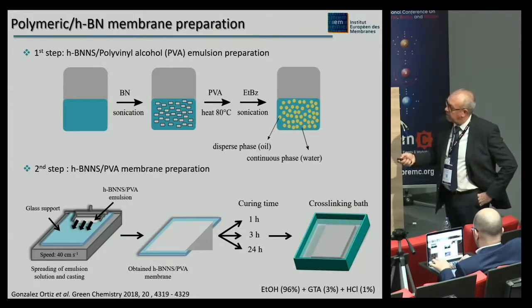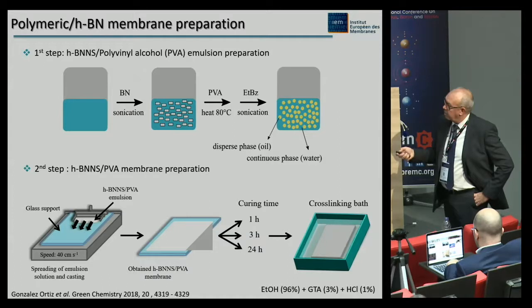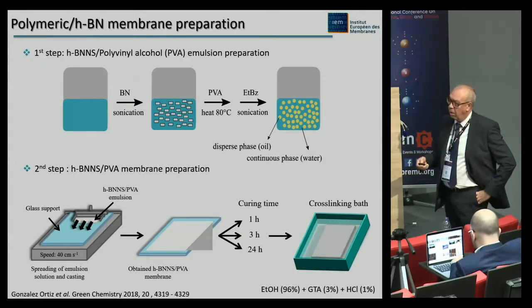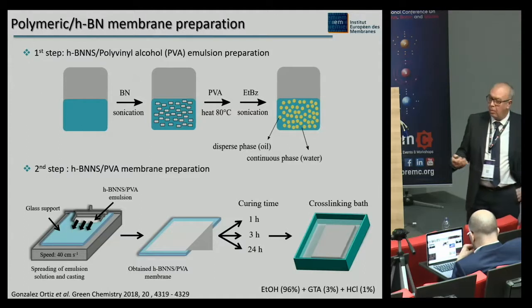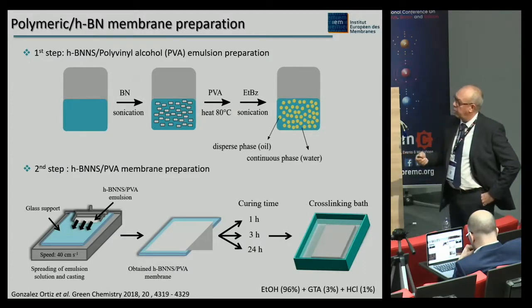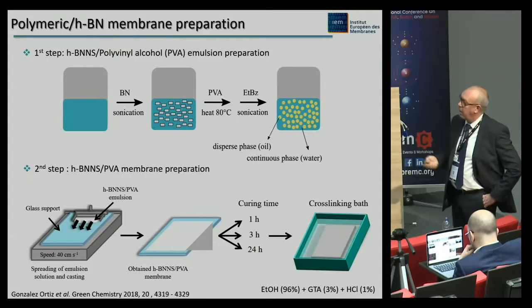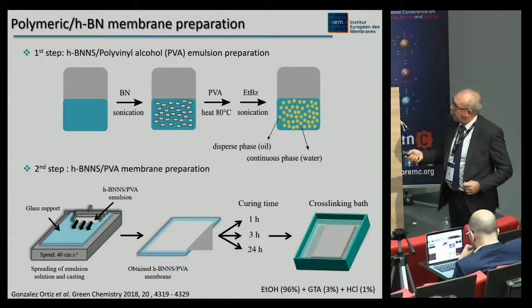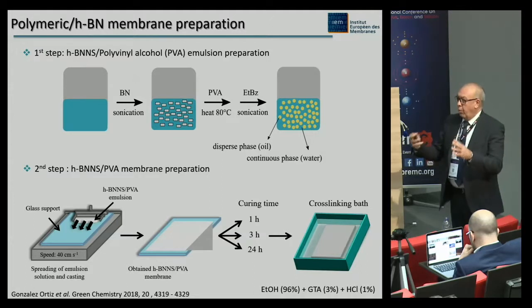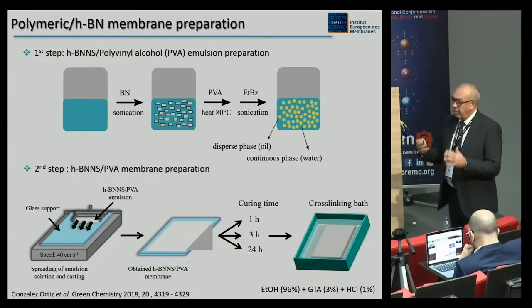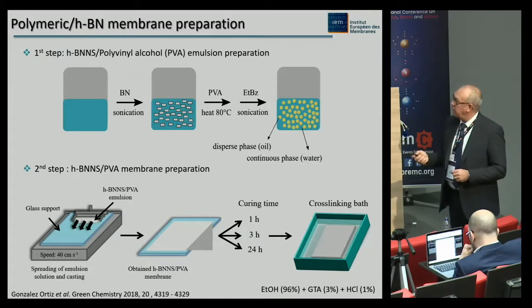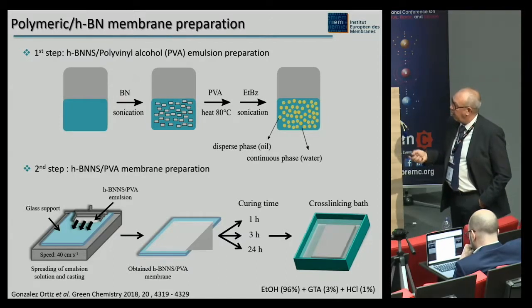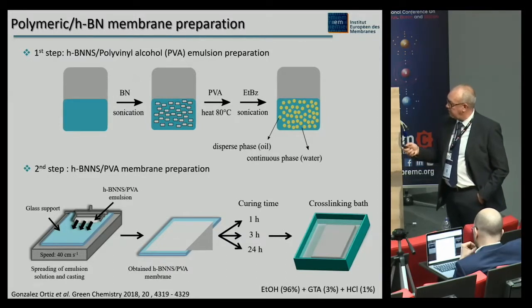So you cast the emulsion on a glass support. The emulsion contains boron nitride and PVA. You obtain the membrane, and you let the membrane go through what is called curing, meaning that you let the solvents, water and ethyl benzoate, evaporate. And after that, you have to provide good mechanical properties to the membrane. So you have to cross-link the membrane using glutaraldehyde in ethanol with hydrochloric acid.